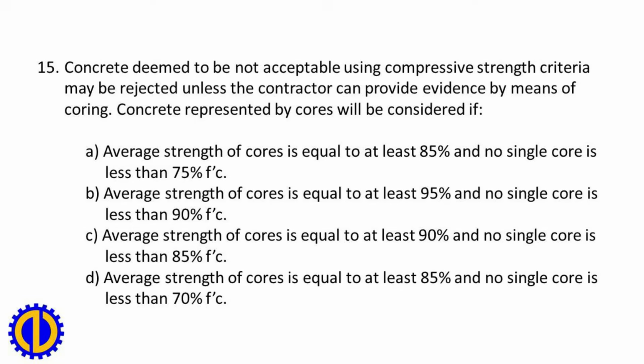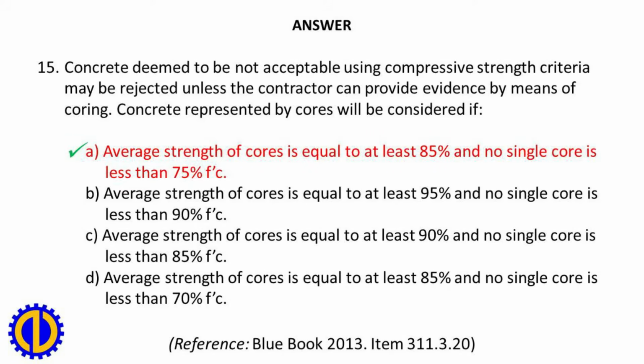15. Concrete deemed not acceptable using compressive strength criteria may be rejected unless the contractor can provide evidence by means of coring. Concrete represented by cores will be considered if: A. Average strength of cores is at least 85% and no single core is less than 75% of f'c. B. At least 95% and no single core less than 90%. C. At least 90% and no single core less than 85%. D. At least 85% and no single core less than 70%. A. Reference, Blue Book 2013, Item 311.3.20.